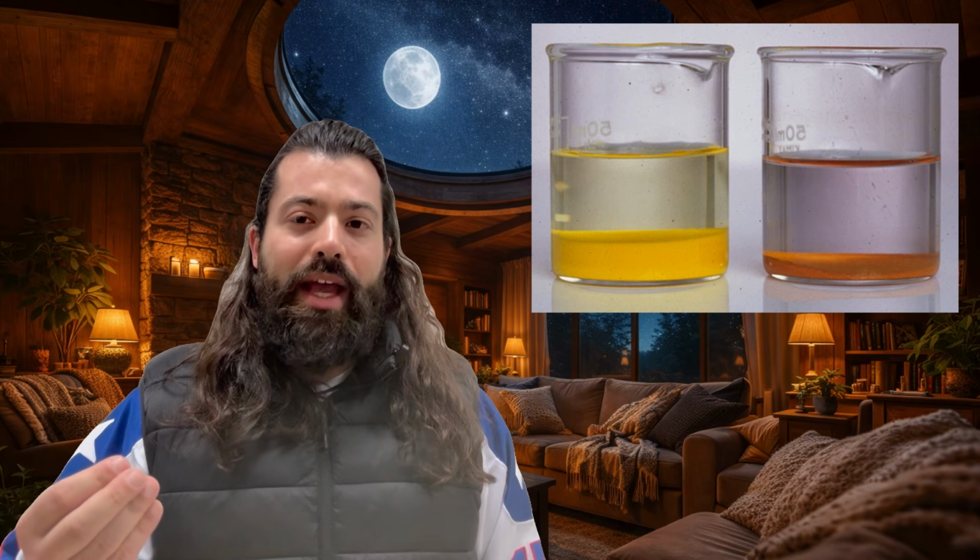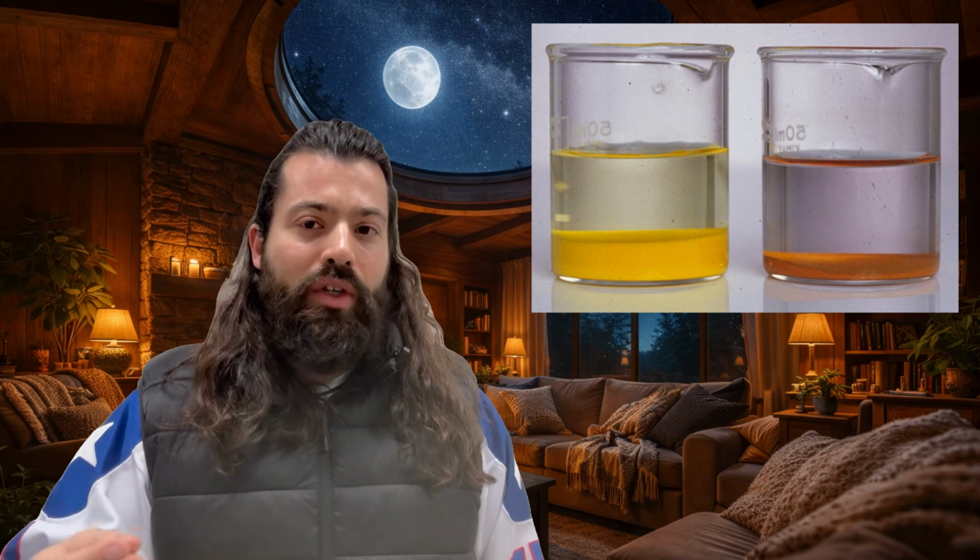After we achieve a satisfactory separation of a rare earth ion from the soup of rare earth ions, it's still in liquid form. We need to collect it as a solid, right? We need to precipitate it at the bottom in the form of an oxalate or a carbonate. After this step, we heat it up to 1000 degrees in order to turn it into its oxide form, which is easy to transport. Then in the future, if we need to use the rare earth in its metal form, we will have to reduce the oxide through calciothermic reduction or molten salts in a cell.